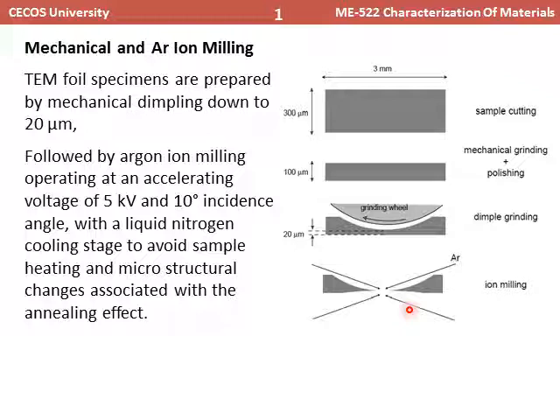The other thing that you have to be very careful about in this sample preparation is that the sample should not be overheated. If this sample is overheated in any of the steps, the first mechanical, second mechanical, third mechanical by dimple grinding, and the fourth by argon ion milling, if there is heat involved, then there is a chance that the microstructure of the material will change. If the microstructure of the material is changed, then the whole process will go to the garbage.